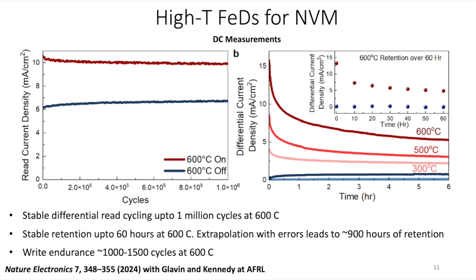A million can be made a billion or a trillion or a quadrillion. I don't think it's going to change. It's just that the students who are doing the experiment got tired after taking a million measurements. Of course, they are automated, but it keeps measuring and takes a few hours to measure a million times. And once it was done, they said, you know what? It's not changing for a million times. It won't change for a billion or a quadrillion times. So they stopped it. Similarly, for hours or time dependent measurements, they did these measurements up to 60 hours, and up to 60 hours, we did not see a long change.